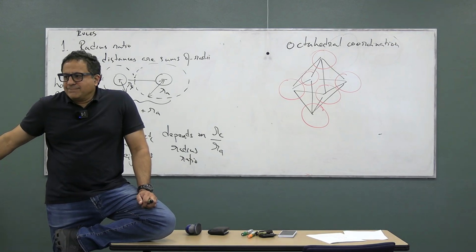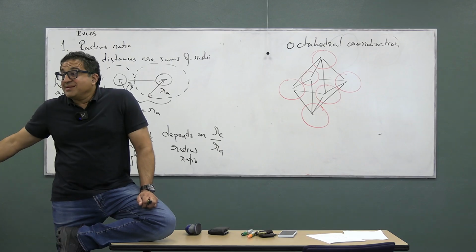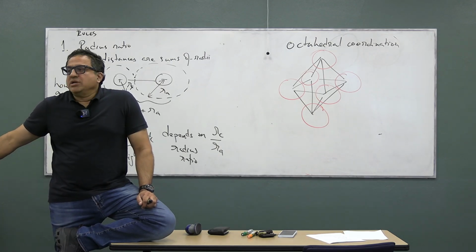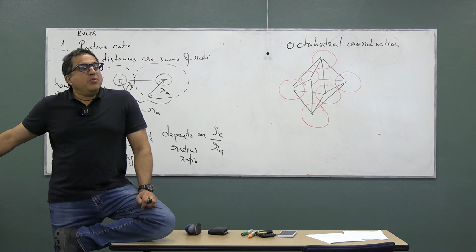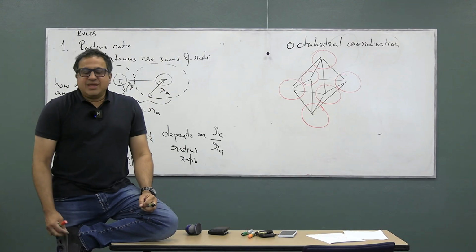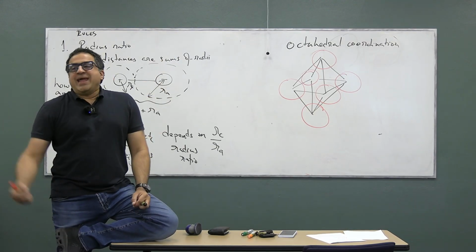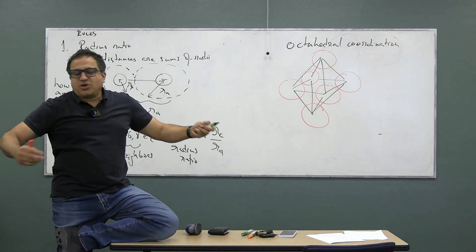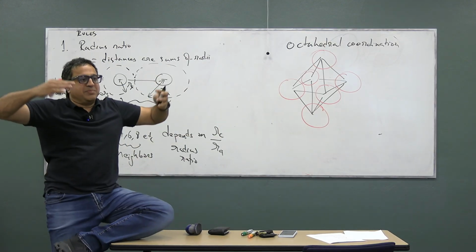Sodium is smaller, because if you take away an electron, the effective charge goes up. You take an electron out, then there's one more proton in the nucleus than there are electrons. So every electron feels a positive charge that pulls it towards the nucleus. If you take chlorine and add an electron, that electron repels all the other electrons that are already there, and it breathes outwards. It becomes bigger.